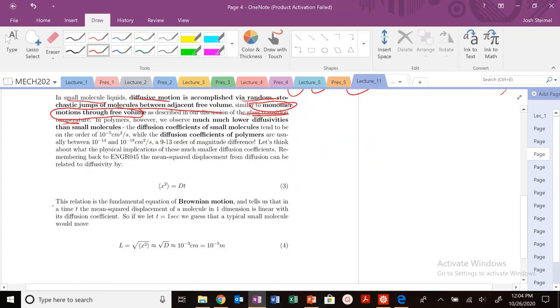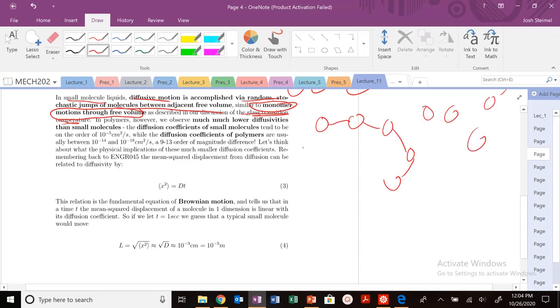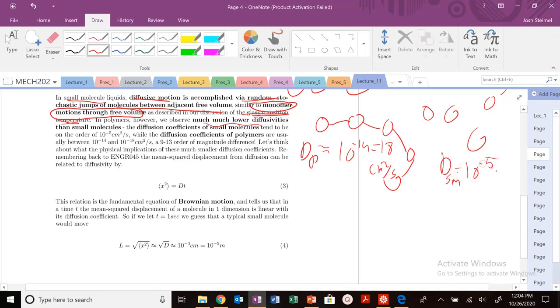For polymers, it's very similar — monomers jump and move through free volume via thermal fluctuations. The key thing is that because polymers are connected monomer units, as opposed to free gas molecules, the diffusivity of polymers is going to be much less — typically on the order of 10^-14 to 10^-18 cm²/s. For small molecules it could be 10^-5 cm²/s. This is a 9 to 13 order of magnitude difference.